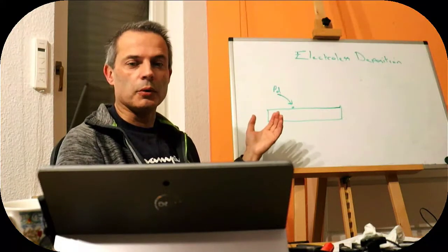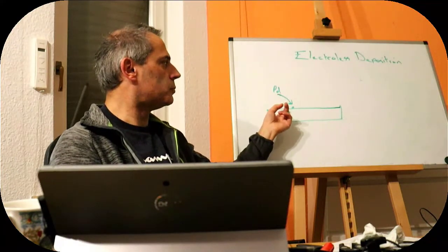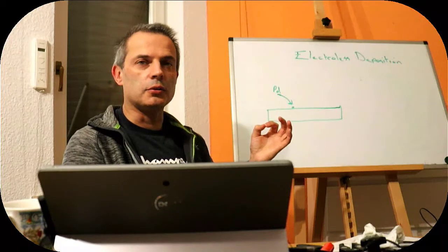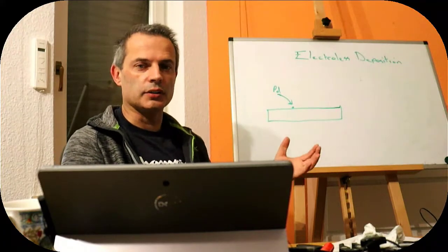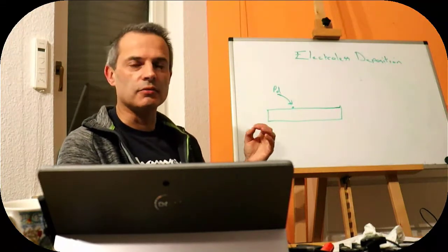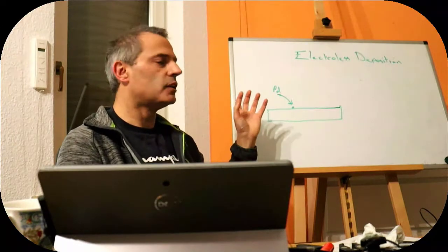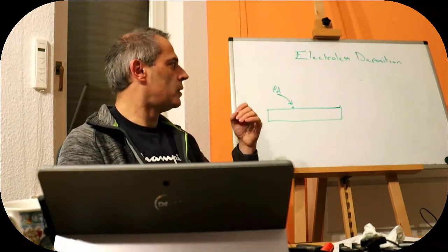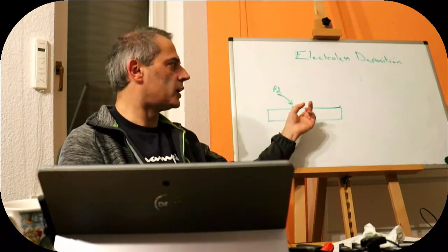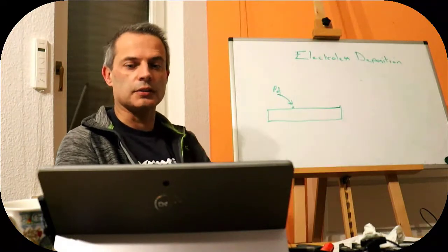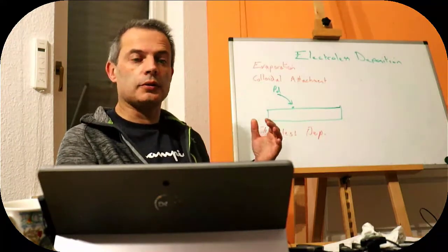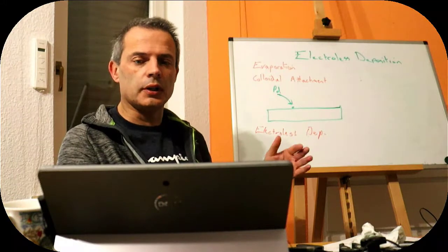So the new problem that we have is we need to attach these palladium particles to the surface, and we have to do that without having any precursor particles. So we don't have all of the advantages that we had in the previous step. We're going to have to put them onto a clean glass or plastic surface. So we're stuck with several methods that we could possibly do that. Let's start from the bottom.